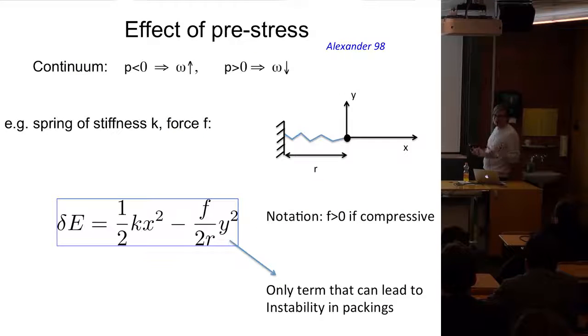Another aspect that matters, and again I think it's very intuitive, is the pressure on the system, and you know this from elasticity, right? If you take thin objects and push on them, it can lead to instabilities like buckling for a thin rod or a thin membrane. If you pull on them, it's the opposite, like the string of a guitar. You're increasing frequencies in the system. And at a microscopic level, you can think very simply about where this term comes from. Here I'm thinking about a spring, but you can think about an interaction between those two particles.